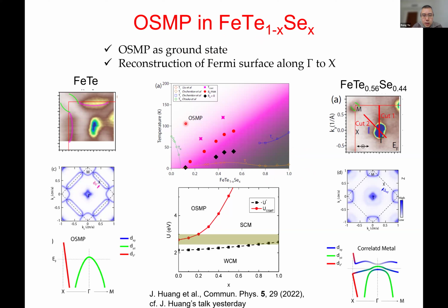This orbital-selective Mott behavior has already been extensively studied in the iron-based superconductors, so it reminds us that there could be some similarity between these two systems. In general, for a multi-orbital system with, say, transition metal 3d electrons, we are interested in whether all these orbitals contribute equally to the superconductivity. But in most cases, the answer is no. There are indeed some systems with particularly strong correlation effects, and the extreme case in the normal state is called an orbital-selective Mott phase.